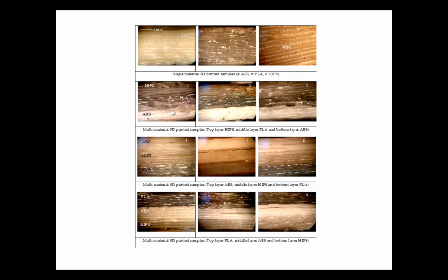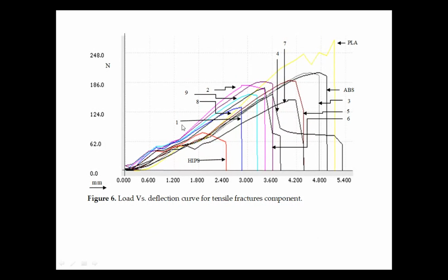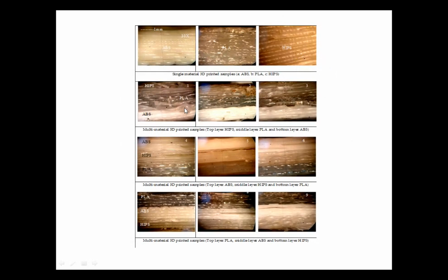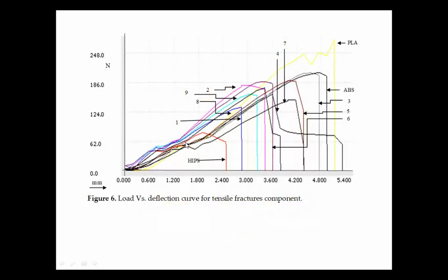Now I can correlate this with the stress-strain diagram. You can see for curve 1, which is shown in blue color, the area under the curve is less. That means the modulus of toughness is less. Also the other mechanical properties are compromised. The reason is the bulging out of this type of material. Whereas if I have the lowest layer of PLA followed by HIPS and ABS in number 4, there are relatively better properties. You can see this curve. This is giving me the better property.